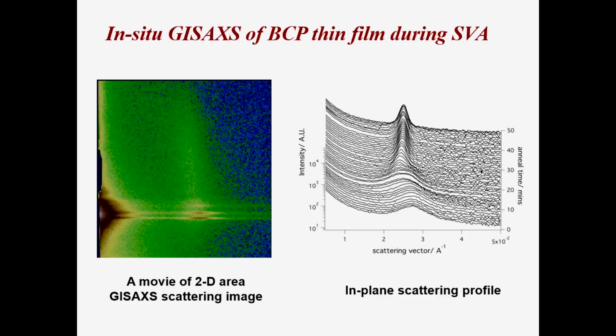And what you see is that this very diffuse reflection shifts into smaller angles. And the reason it shifts into smaller angles is that the size of the structures is getting bigger. You spin coat a film, you put it into a non-equilibrium state, you introduce a solvent, and then with the introduction of solvent, the molecules can start to separate.